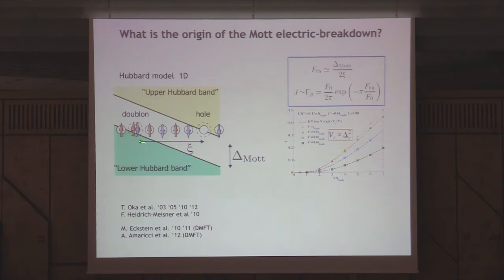So the idea is that you tilt these bands applying an electric field. So this is the Mott gap. This is the delocalization of the doublons. These are virtual excitations in which particle sites can become doubly occupied. But of course, since this system is an insulator, this electron cannot go very far, within a length scale of the order of xi. It just comes back.